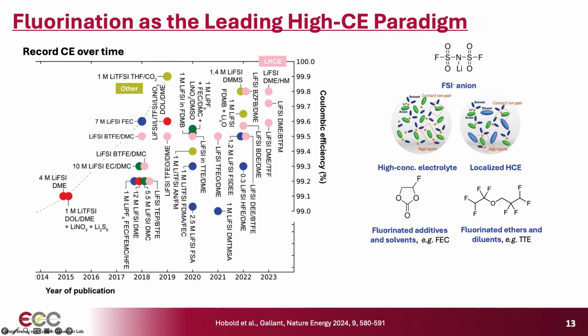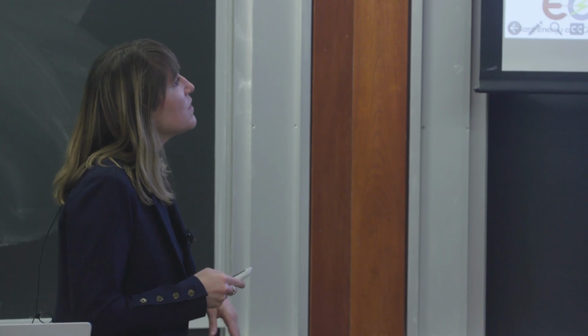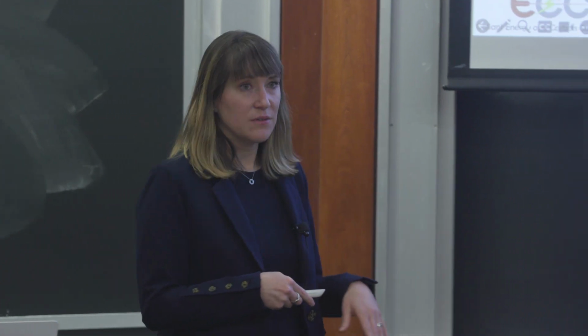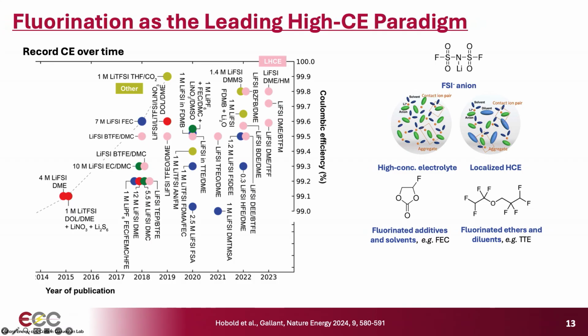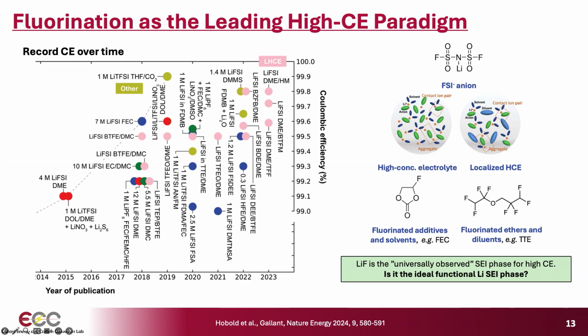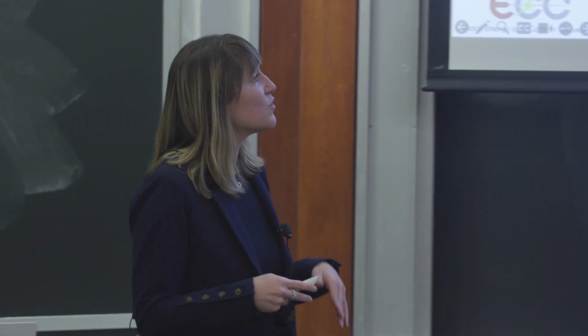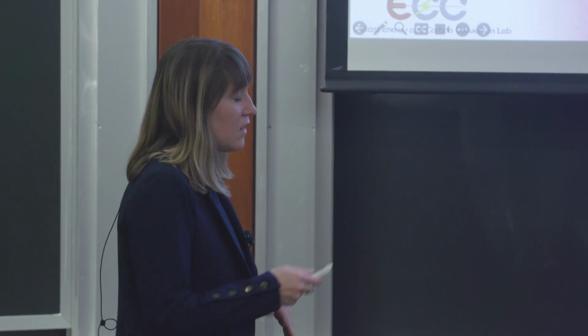So I mentioned this at the outset, but I want to underscore it here. All of our high-performance electrolytes tend to rely overwhelmingly on the FSI anion, which has fluorinated, and also combinations of fluorinated additives, solvents, and diluents, okay, such as the example shown here. And so it's actually not too surprising when we go to characterize these SEI that we, using other methods, tend to find lithium fluoride as pretty prevalent, especially in these high-performance electrolytes. So this has led to a kind of rule of thumb or a belief in the field that lithium fluoride is the most universally desirable functional lithium SEI phase. But that hadn't really been scrutinized in a quantitative way, and now we had the tools to do that.